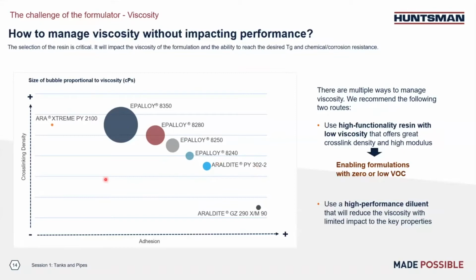So the product I want to highlight in this slide is XTREME PY2100. So you notice this one has a very small bubble, because this resin has a very low viscosity. Its viscosity is even below 1,000 centipoise at room temperature. And this one also has very high functionality, giving us very good cross-linking density. So this is exactly when we talk about using those low viscosity but high functionality resins, they give us the opportunity to make formulations with zero or lower VOC.